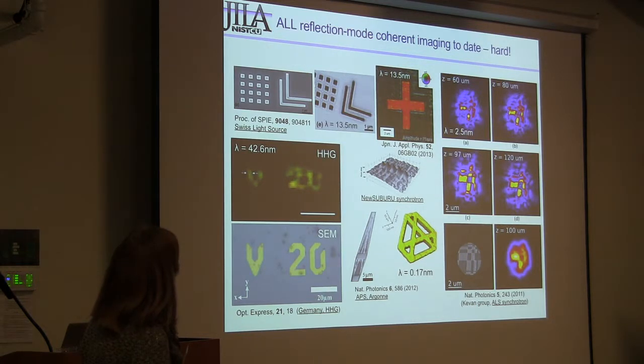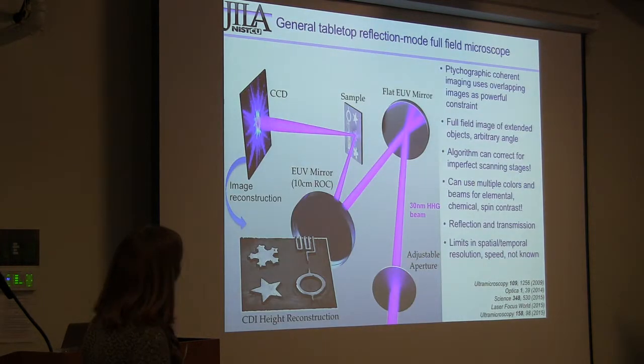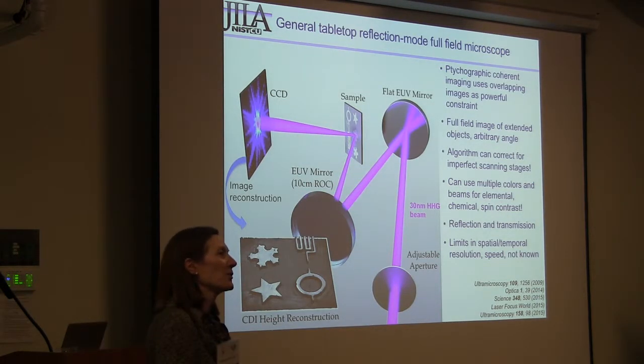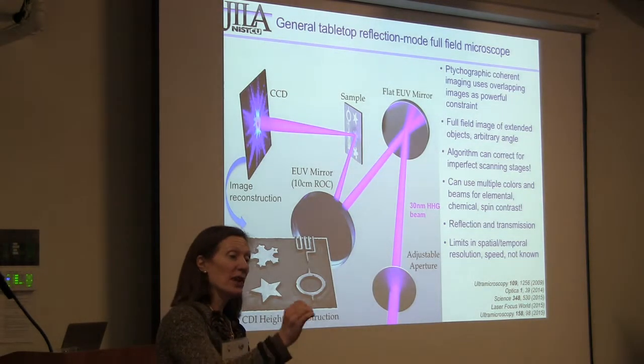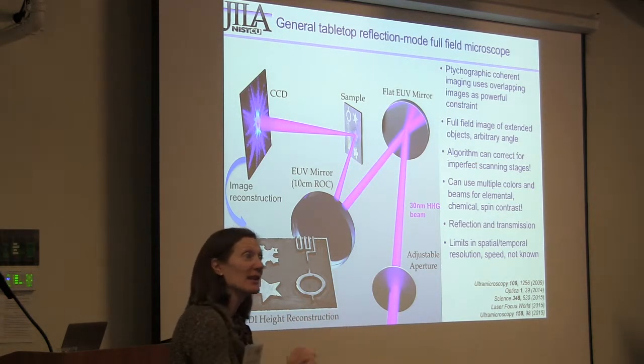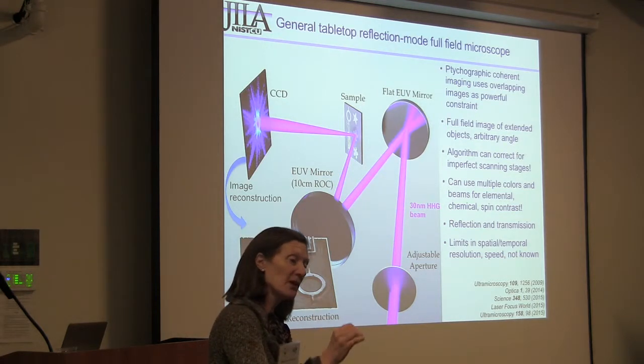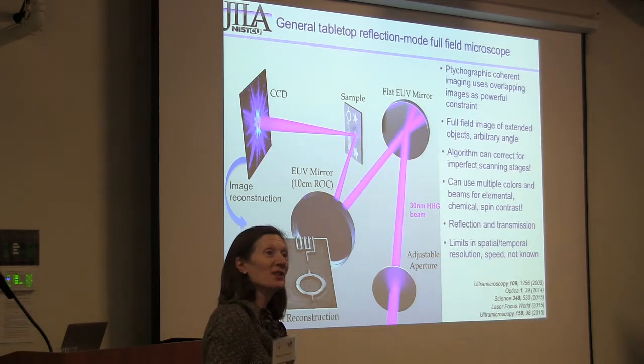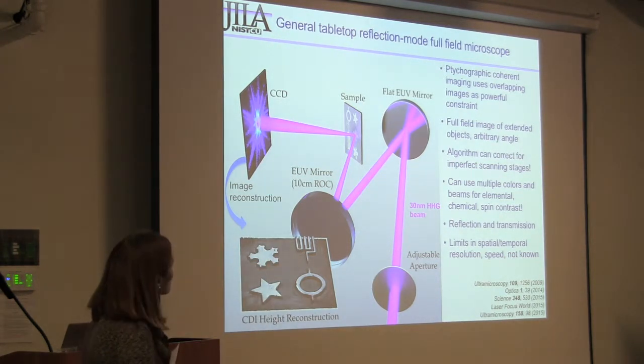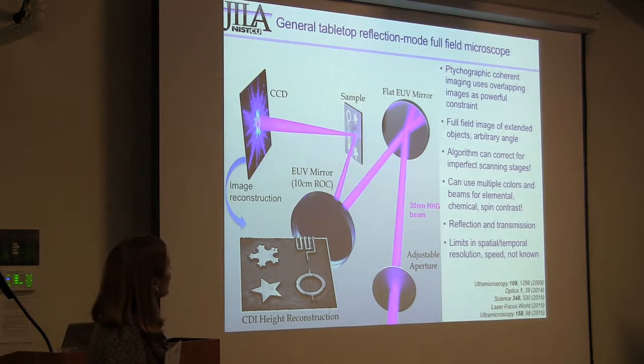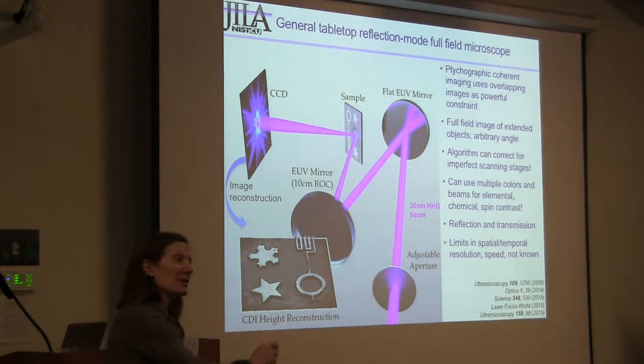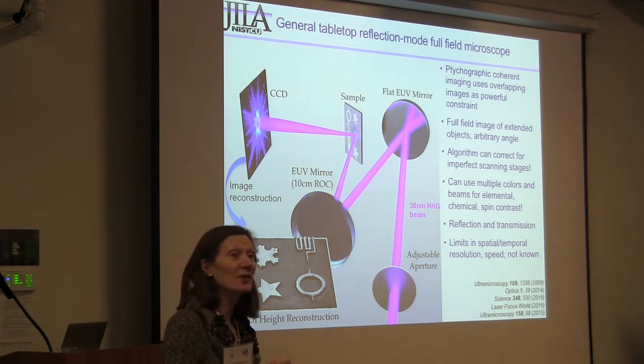But what took this work, including ours, and made it even better, was a new technique that's called ptychography. It was developed by Rodenburg's group in the UK, and it really works as a really tight constraint, so the algorithm doesn't stagnate. So all you do in ptychography is take overlapping images and scan like you're taking a scanning image. But if your beam has 30% overlap with the adjacent spot, it turns out that so constrains the algorithm that it is forced to come up with the actual object that generated those diffraction patterns. And it is so powerful that it actually corrects for it if your scanning stage isn't taking equal steps, it can figure that out. And it also gives you the amplitude and phase of the illumination beam.